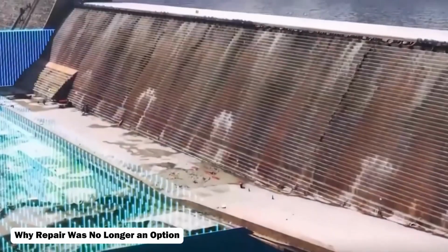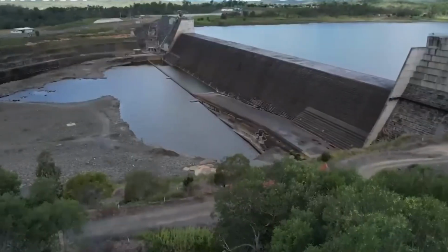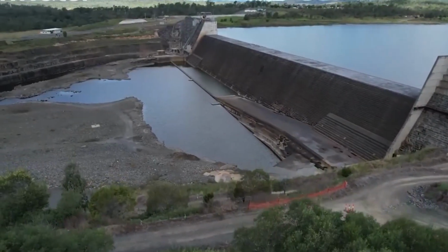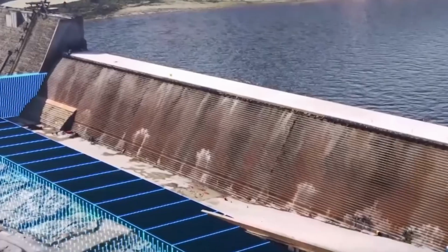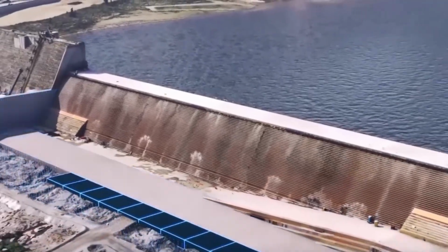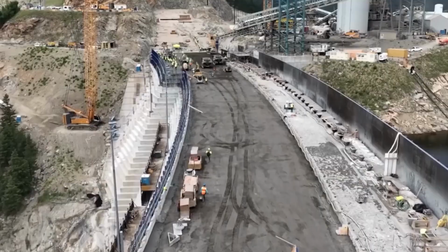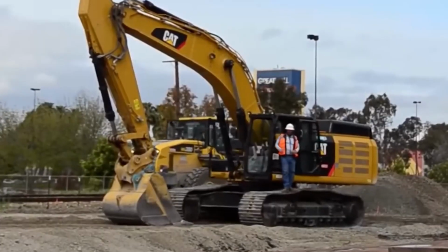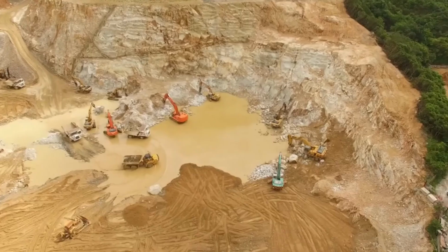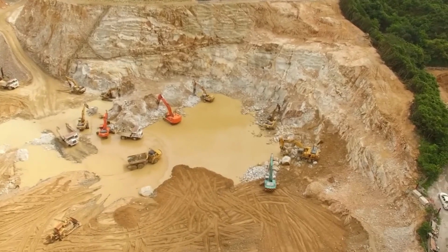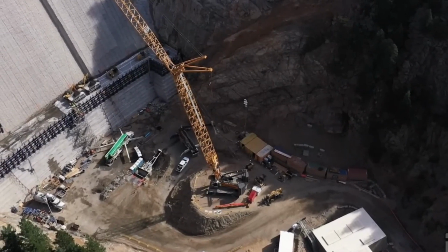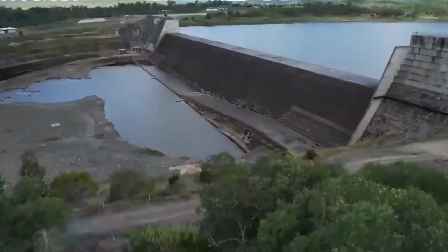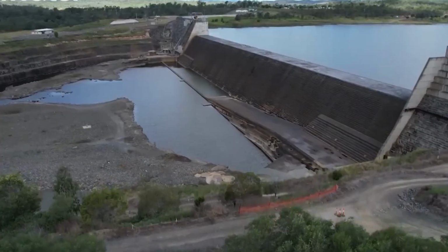Why repair was no longer an option? At first glance, strengthening the dam seemed possible. Why not reinforce the spillway, improve drainage, and restore the height? The answer lay inside the concrete itself. Forensic testing revealed that the roller-compacted concrete was far more porous than expected. Water was traveling through the dam, dissolving and washing out cement in a process known as leaching.